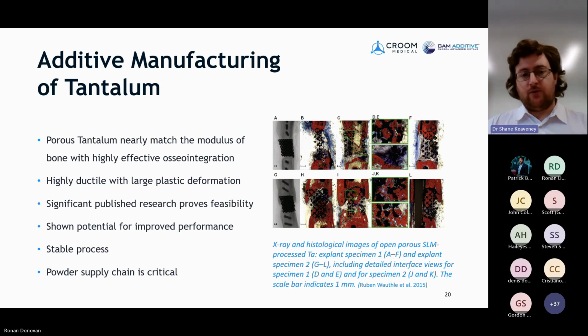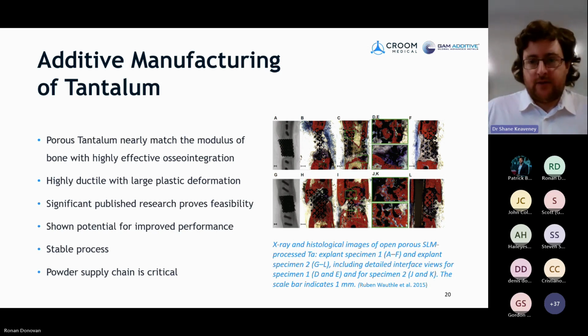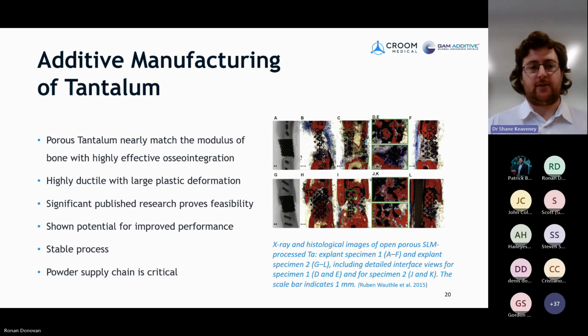So the other 2 points here, which are quite important for our collaboration with GAM, is that this is a very stable process, the printing of tantalum, and I'll show results around the powder stability during the process, but the powder supply chain is also quite critical to the entire system. So again, for additive manufacturing, where we have a powder source, the powder supply is quite important. And if we look at the last couple of years where there's been major supply chain issues, and especially if we look at titanium, there's quite a demand on that, and there's been issues there in the supply chain.